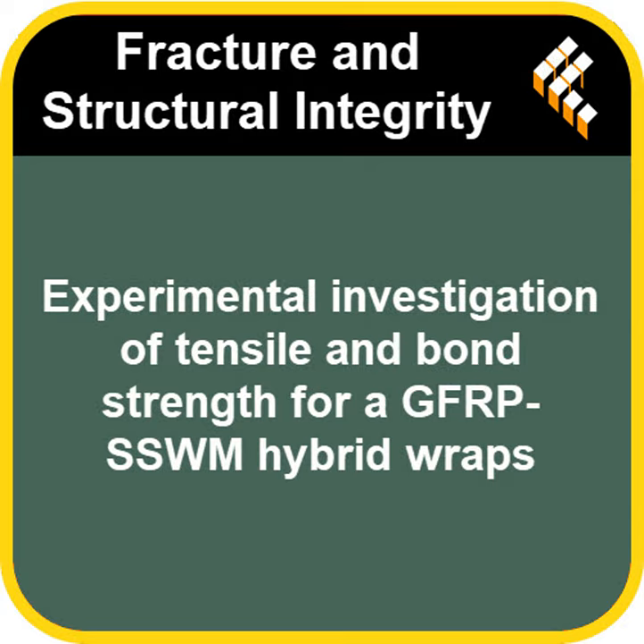And GFRP is just one type. Right. It's part of a family. Yeah. You've got aramid, basalt, carbon, CFRP, and then glass FRP, the GFRP. Okay. And GFRP is interesting because, well, two main reasons. It has a high strain capacity. It can stretch quite a bit before it breaks. Right. And it's really cost effective. I mean, compared to carbon FRP, it can be 10, even 30 times less expensive. Wow, 10 to 30 times. That's a huge difference. It really is. Makes it much more practical for large-scale jobs.